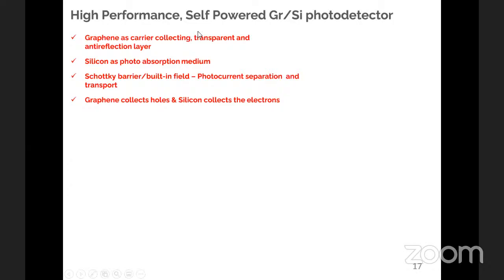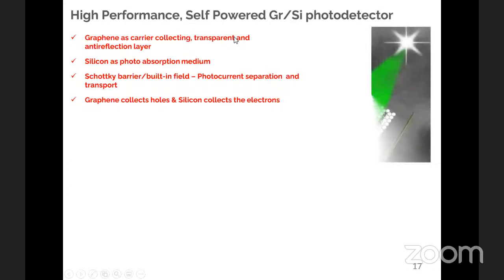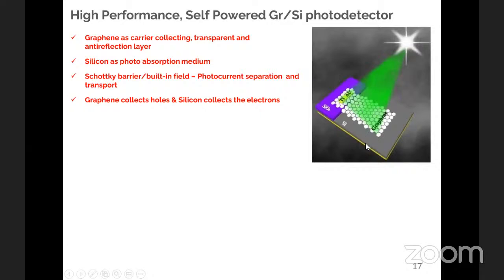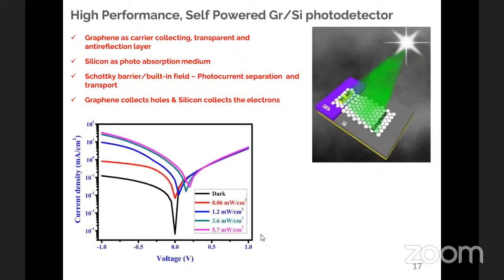After demonstrating this graphene-silicon Schottky diode, I applied these devices as optoelectronic devices, that is, a photodetector. I shine light on the graphene and semiconductor. Here the graphene acts as a carrier collecting layer, and because it is very transparent, also as an anti-reflection layer. Silicon acts as the photo absorption medium, and at the interface between the graphene and silicon, as I mentioned before, the depletion region or built-in field will help the device generate a photocurrent upon photocarrier separation. This is the IV characteristics of the devices under illumination with different laser power.